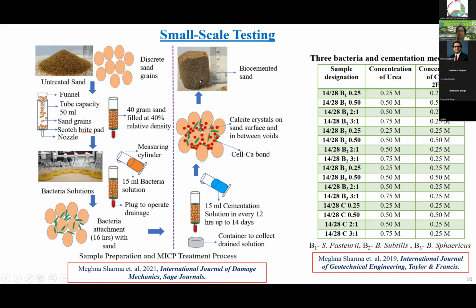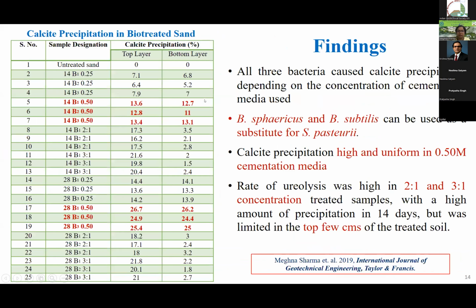Means the whole depth got precipitated. Okay, and in other samples, where the urea concentration was higher than the calcium chloride concentration, the precipitation was there only at the top layer, and at the bottom layer there was very little precipitation, 1-2%. So that's why we need to choose what our application is and where we need to apply it. This is because of the rate of reaction: if the urea amount is higher, the pH will increase significantly at a faster rate, and the precipitation will happen quickly and it will create bioclogging.